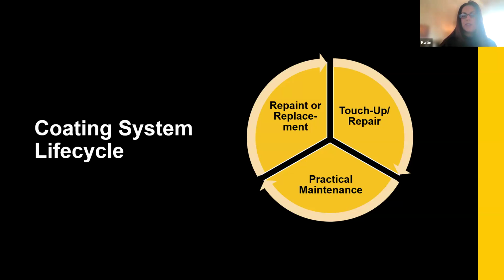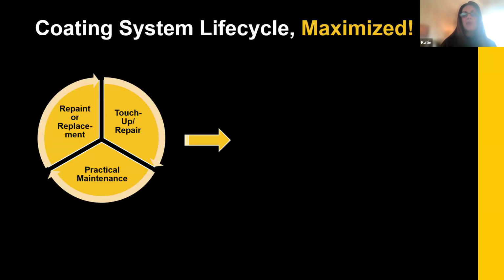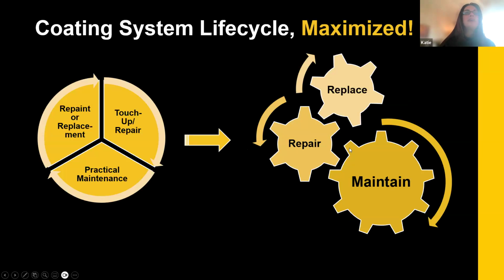If we go back to those original statistics, when we get to the maintenance phase, we can achieve 50 to 80% more of coating potential if we make a good decision with an overcoat. And that's versus 10% or less if we make a bad decision. So it's really important that we make those good decisions. And if we can extend or spend more time in the repair and practical maintenance phases by implementing better coating selections, then we are going to maximize the amount of time we spend in these areas. And therefore, we're going to help reach our goals to provide more value to the end customers by maximizing that service life.